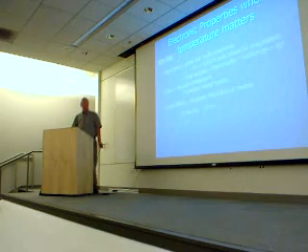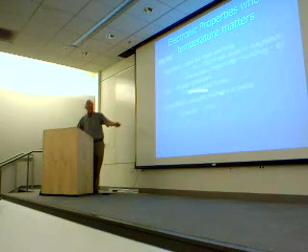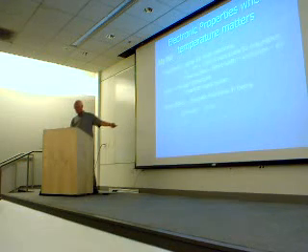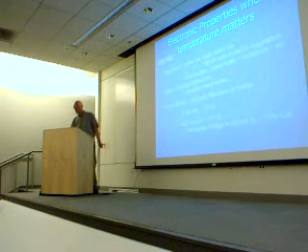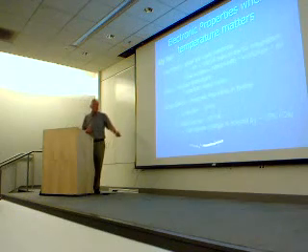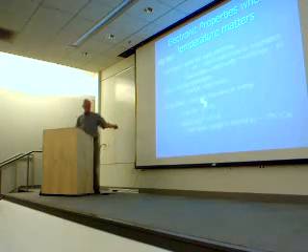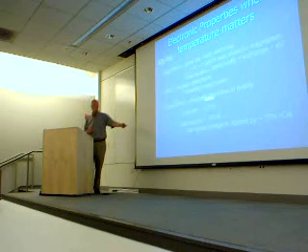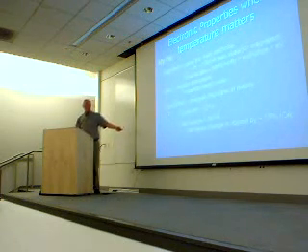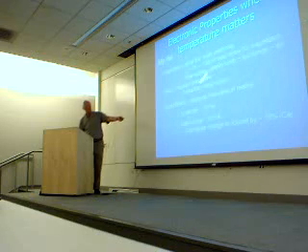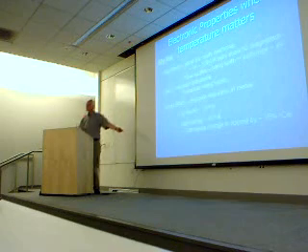But if you look in the literature, some of the famous systems that exhibit this Kondo effect, which is a resistance minimum that's observed at low temperatures, it might be a millikelvin. And not so well known is that there can be others at 1,000 Kelvin. So these many-body effects can span orders and orders of magnitude, even though the basic fundamental parameters like the electronic interactions and bandwidths don't change anything like that much.